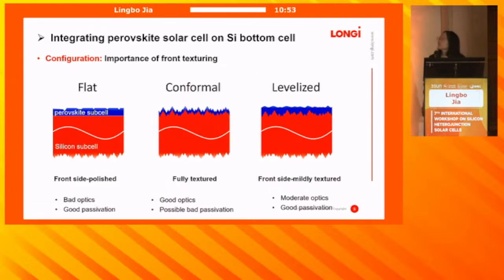And also, the texture of the silicon structure can impact the device efficiency. The current high-efficiency silicon solar cells feature fully textured structures to maximize sunlight absorption. The tandem solar cells utilize front side polished silicon substrates, which facilitate the deposition of uniform and fully covering perovskite layers. But the inadequate optical management will limit their efficiency.